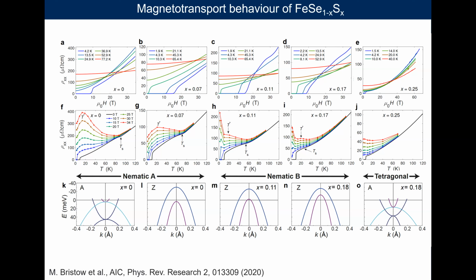Now, when we go to higher concentration, when we are bringing the inner hole band crossing the Fermi level, now there is an opposite effect. The resistivity has a strong upturn, as if there is another anomaly happening there.